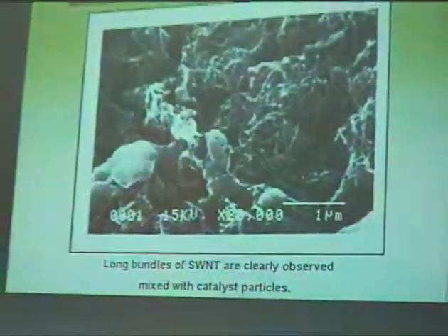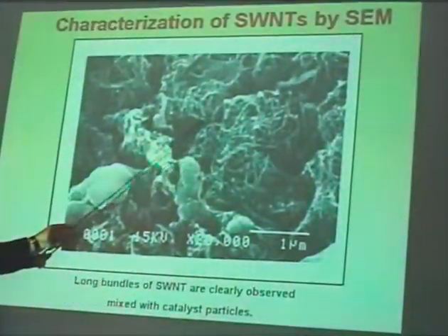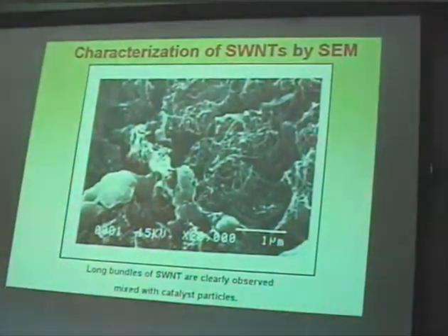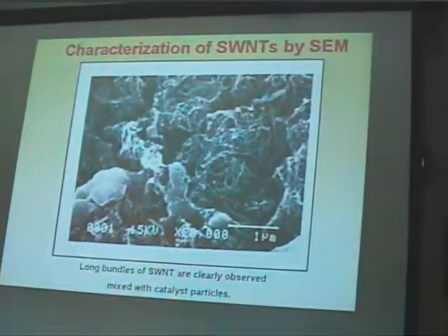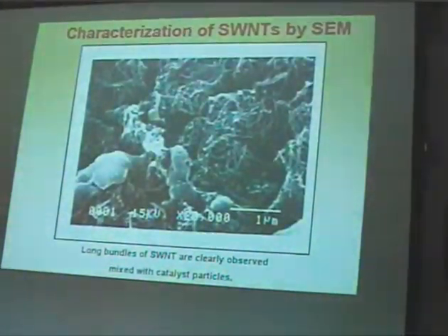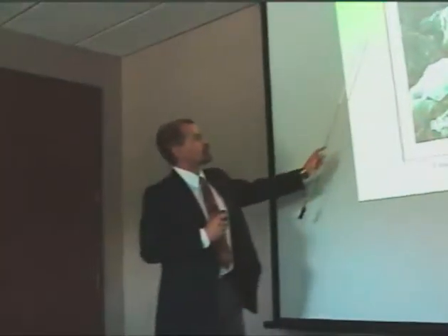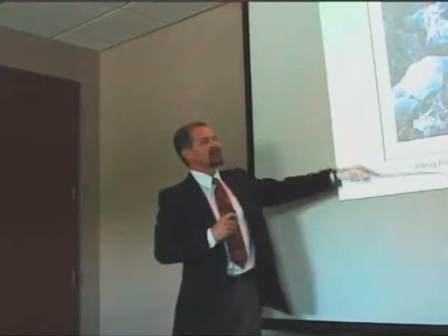This is an SEM picture just to show you how we produce these carbon nanotubes. They appear in bundles. Each of those will be a bundle. And of course, you have the silica that after we produce it, we need to remove. We have found a way to remove the silica very easily by leaching with a basic solution of sodium hydroxide. So we remove in that attack essentially 99% of the silica, and then with a subsequent acid attack, we remove the cobalt and the moly.